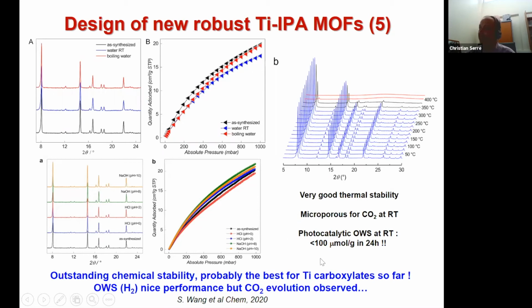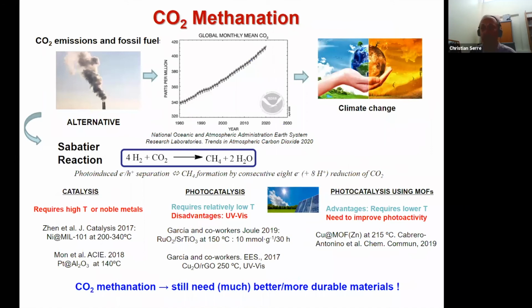And initial tests, this time not for hydrogen evolution, but overall water splitting, were quite promising. We have also around 100 micromole without any optimization in 24 hours. But our colleagues observed some CO2 evolution, and that is why they did not pursue in this direction, and they decided to focus on another application, which is CO2 photomethanation.